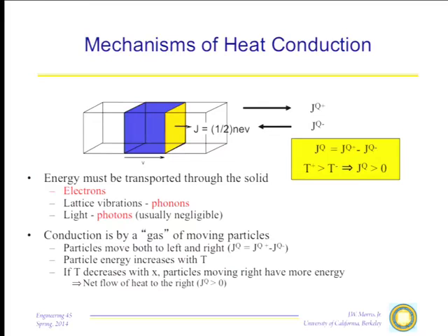They are important actually in 2 places in materials. At very, very high temperature, because the photons are really excited, you can get a significant photon contribution, optical contribution to thermal conductivity. Ironically, the other place you can get a big optical contribution, and I just mentioned this in passing, is at very, very low temperature. If you look at people who are putting together superconducting magnets, for example, the big ones, that have to operate at 4 degrees Kelvin, and you look at the insulation in those superconducting magnets, you'll observe that the insulation on the vacuum seals is always very shiny. The reason it's shiny is to reflect photons.